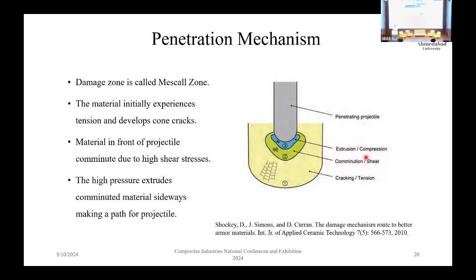If I have that teacup, I can't bend it. Had it been plastic, I can comfortably bend it. So as a result, there will be a lot of damage. Now, the good part is that the tip of my bullet is damaged because of this abrasive tool. A lot of high hardness material, that steel, is quite worn, that is, grinding has been done, but now we have got a lot of debris of this ceramic along with two or more pieces of left out bullet, which are still moving at a very high kinetic energy.